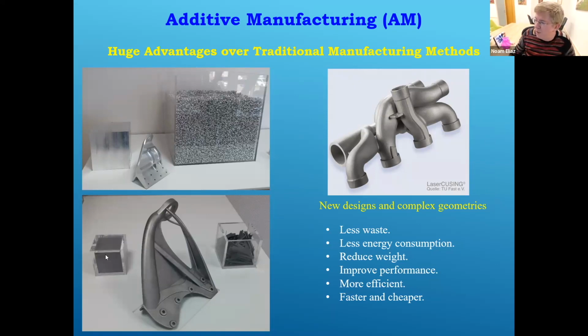On the left-hand side, you can see the batch, the raw material, the powder that is needed for this specific part. And on the right-hand side, you can see the supports or the waste that were generated using this process. Again, they are not to the same scale, but although aluminum is lighter, thanks to this design and the reduction in volume, the part at the bottom is actually lighter than the part at the top and has better specific mechanical properties. And here on the top right, you can see a part that was printed in one piece, no weldings, no other joints, no riveting, etc.